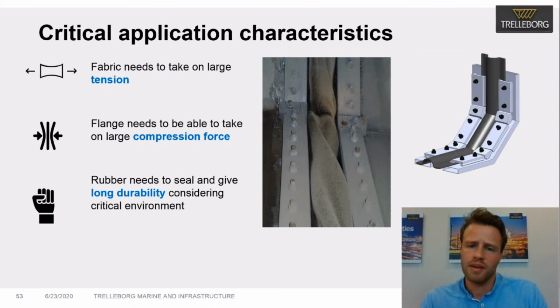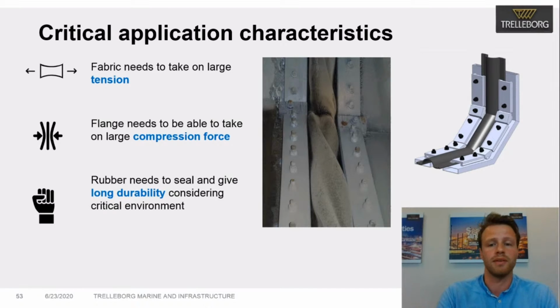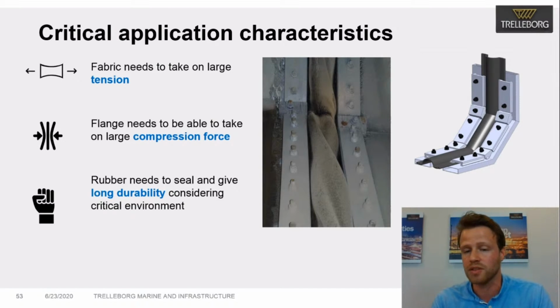So this is an omega seal being installed. It looks a bit warped at first glance. However, this is perfectly normal behavior of the seal. It shows that this type of seal can accommodate a lot of movement during its lifetime. What probably happened in this situation was that during the positioning of the elements, they were slightly tilted. But those building tolerances are definitely something you have to take into account while designing an omega seal.